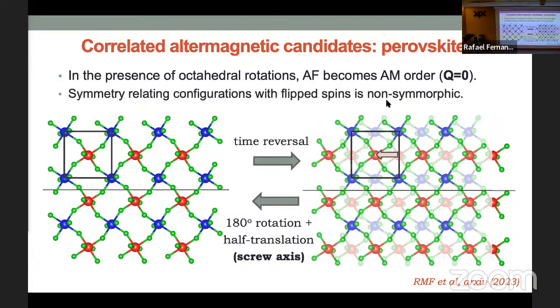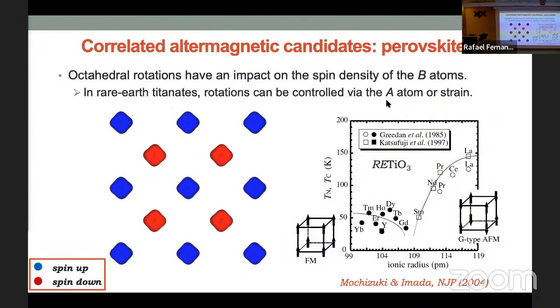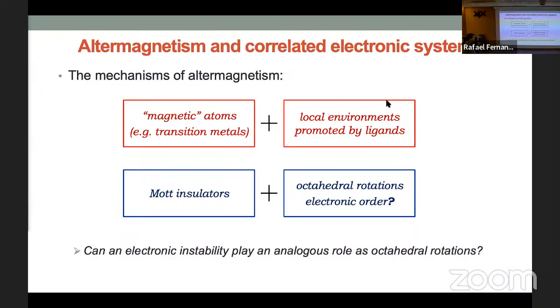So this is another place where you can look. Excuse me, and a particularly promising series of perovskites are these rare earth titanates, because here you have precisely this Pnma structure, and the size and the amount of octahedral rotation depends on the size of the rare earth. So you can control with rare earth, you can control with pressure, strain. So there's lots of tuning parameters, okay? And this is just a DFT calculation showing what happens when you start rotating, with the spin density, and why it's no longer just an antiferromagnet. Okay, so this is one way where you can get this Mott insulator and octahedral rotations. But what if I don't want to invoke any structural degrees of freedom?